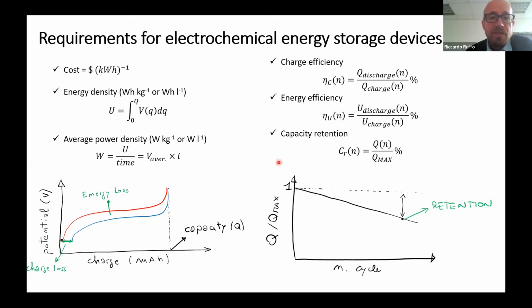Then an important parameter is the capacity retention, which means if I fix to 1 the maximum charge that I can get from my battery, in how many cycles is my charge lasting without a significant decrease of the charge. An acceptable value, for example, for automotive application is 20% of charge lost after 1,000 cycles.